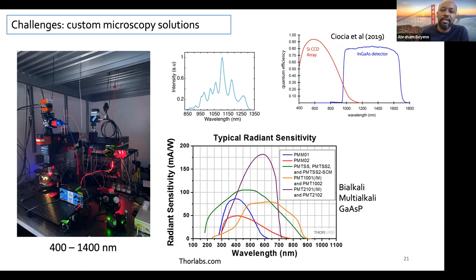But this being an OIG, optical interest group, I thought I would be stupid not to bring this up, which is that there is a bit of a challenge in terms of using these materials, right? I talked about how advantageous it is to have fluorescence in this region of the spectrum, but there is also a huge disadvantage. And this is the fact that emission in this range of the spectrum is completely undetectable with silicon-based technology. So you can see that the QE, quantum efficiency, of these detectors falls off in this region of the spectrum that we actually are interested in.